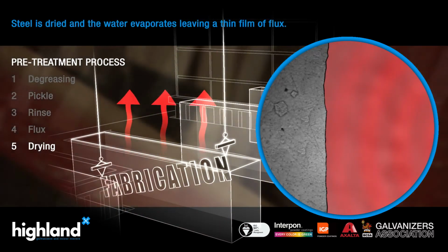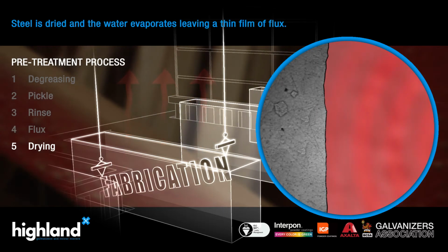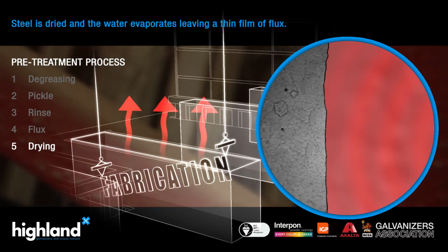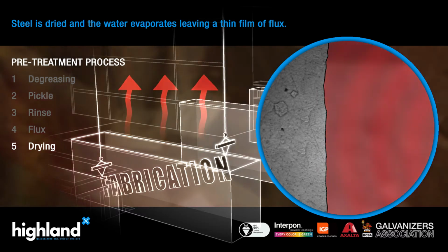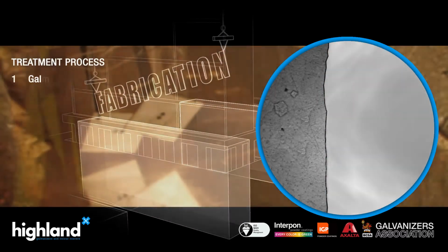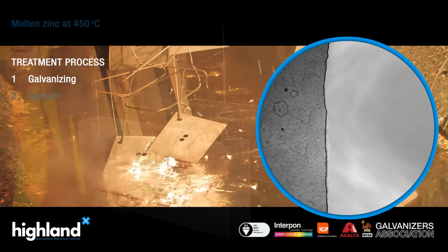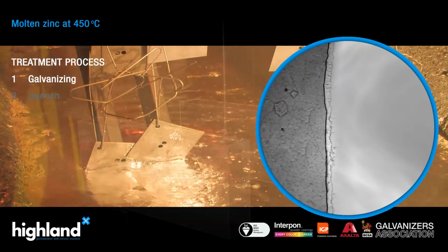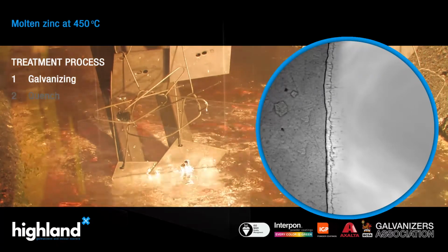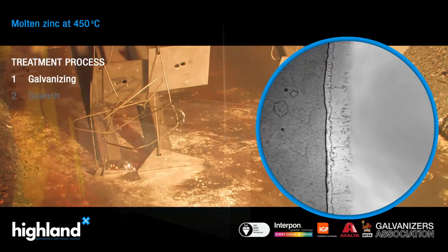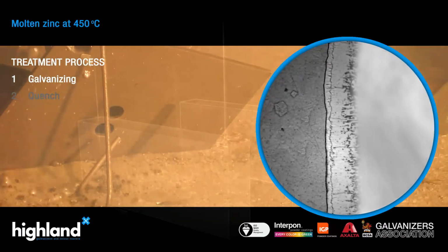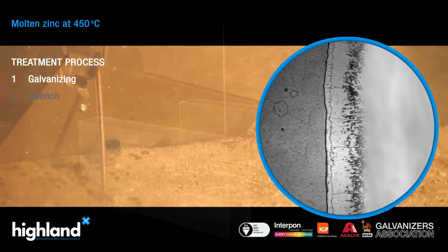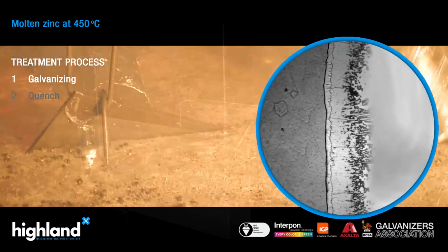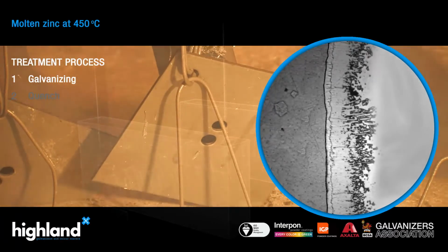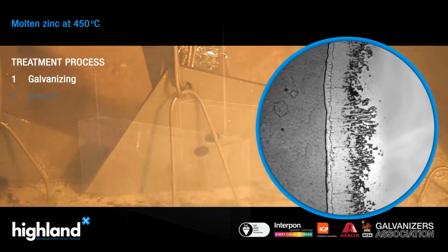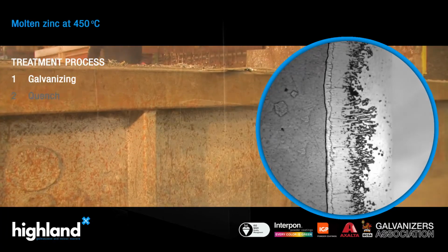The last stage in pre-treatment is to dry the steel in preparation for immersion in the zinc. The steel is lowered slowly into the kettle of molten zinc, which is heated to 450 degrees Celsius. The resulting metallurgical reaction creates an alloy on the surface, forming a corrosion protection layer on the steel. The small explosions are created by very small amounts of moisture rapidly evaporating.